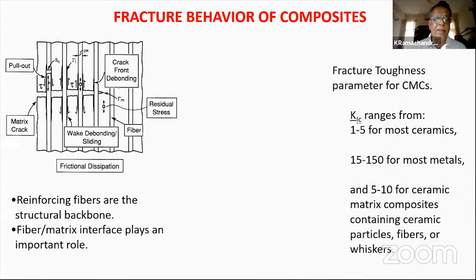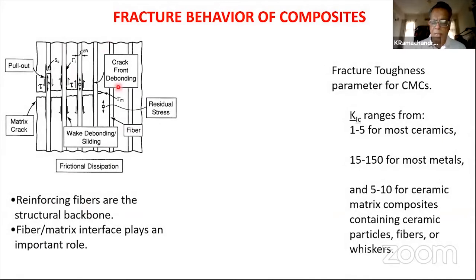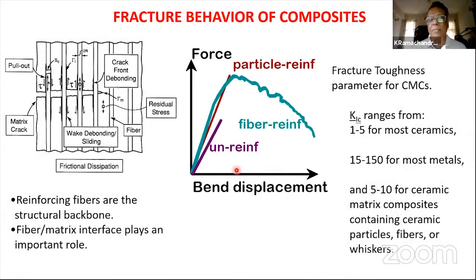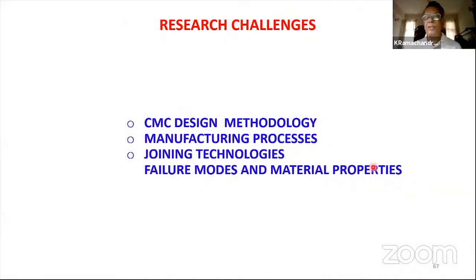We need to understand the failure mode mechanisms, and also, for example, the way they behave when load is applied at different temperatures. And we must be aware that the fracture toughness of ceramic matrix composites is quite low. It's about 5 to 10, as compared to 15 to 150 for metallic materials. So this is something which we must keep in mind. And there is an urgent need to overcome this big gap in CMC technology, the ceramic matrix composites technology.